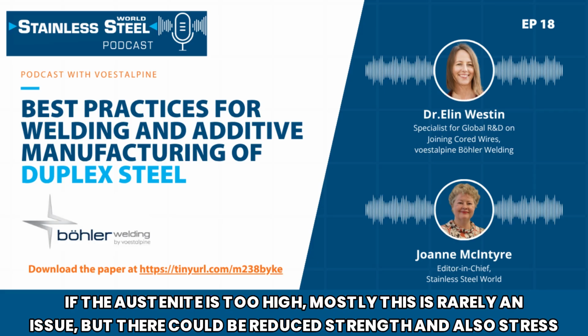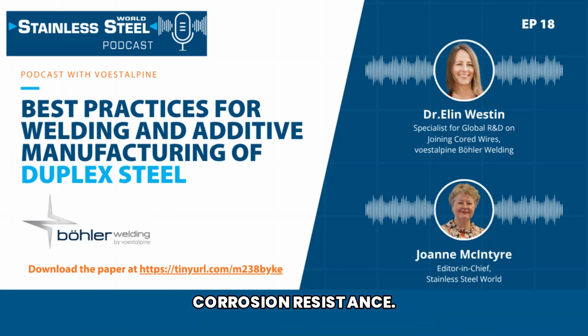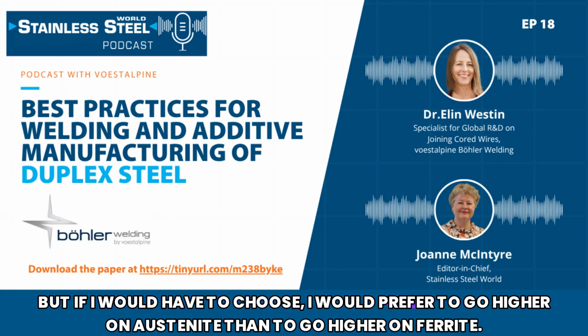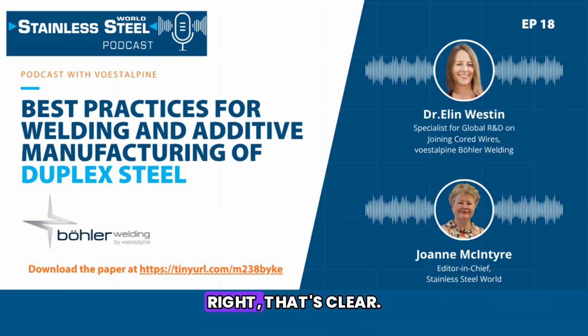If the austenite is too high, mostly this is rarely an issue, but there could be reduced strength and also stress corrosion resistance. But if I would have to choose, I would prefer to go higher on austenite than to go higher on ferrite. Right, that's clear.